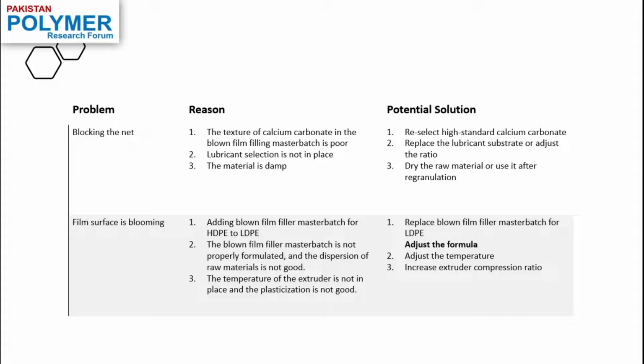surface of the material. So the potential solutions can be that you should be using the right master batch for the right resin, adjust your formulation, adjust the temperature, and you can also increase the extruder compression ratio if you have eradicated all the above issues and problems, but you're still getting a surface that is blooming. You can check the extruder compression ratio, because if the extruder's compression ratio is not in place, you're not getting a proper dispersion, and that can also cause a surface blooming of the film.